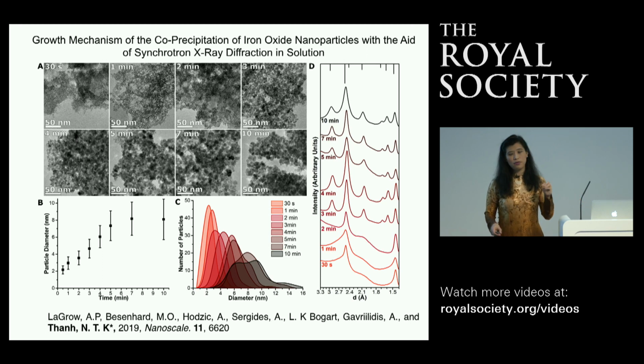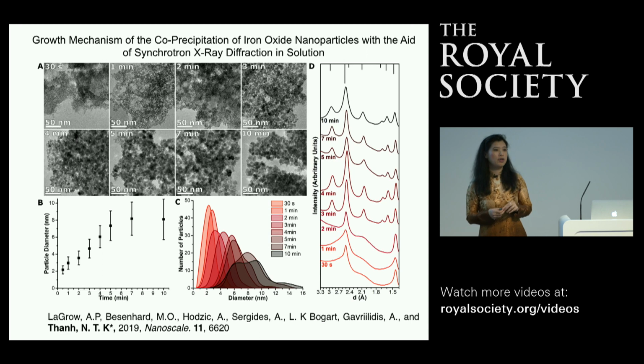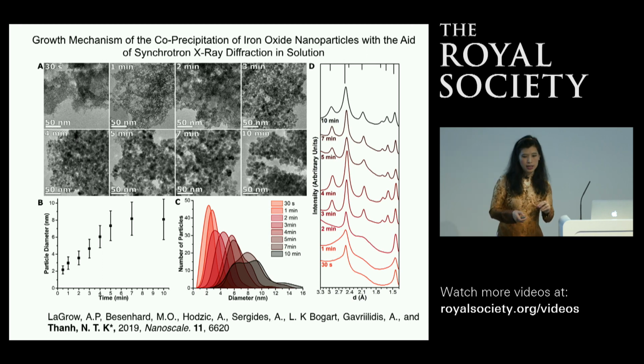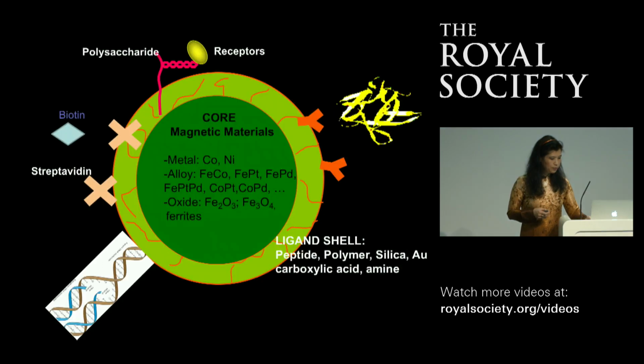But the trick for my demonstration was that the kettle was already pre-boiled. So you've got 100 degrees, it's very hot, and you put it into the reaction, so it reacts immediately. In this case, the reaction we use is at a lower temperature.